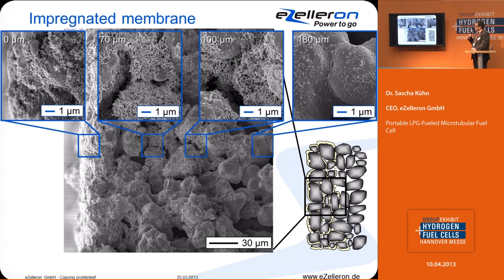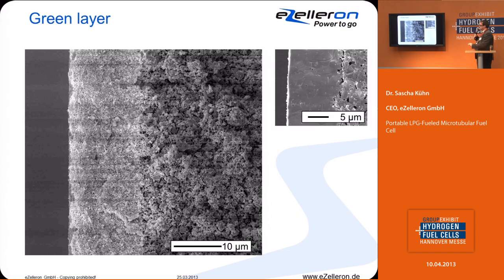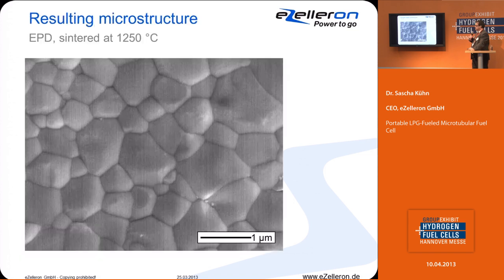You can see that more than 180 microns deep we can come with the nanoparticles, so we get very good adhesion of the green layers with a high green density. And here you can see already that it's almost pore free, and the pores are always below the wavelength of the light, so the layers are bright and shining and seem to be transparent.